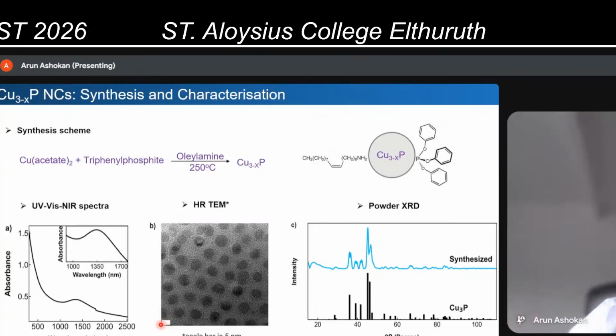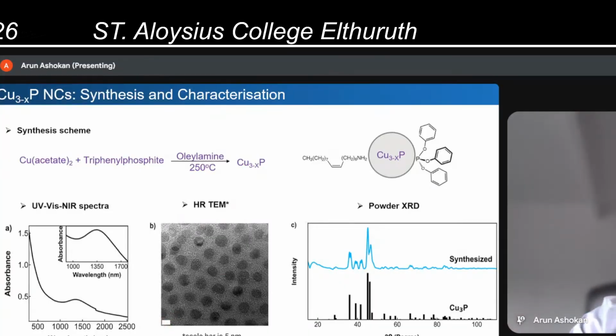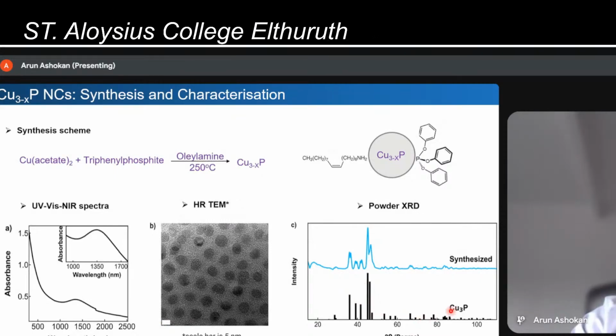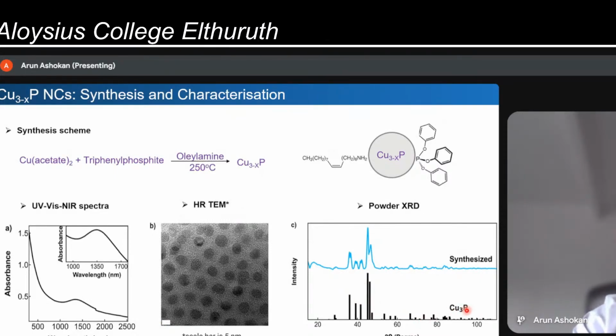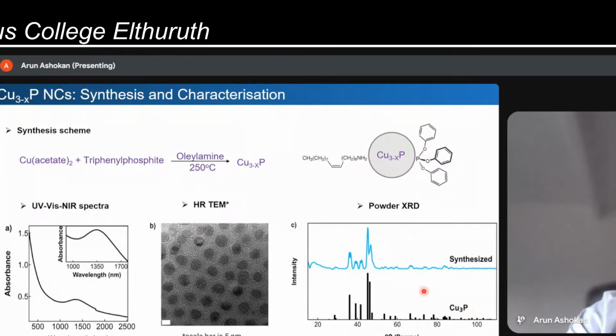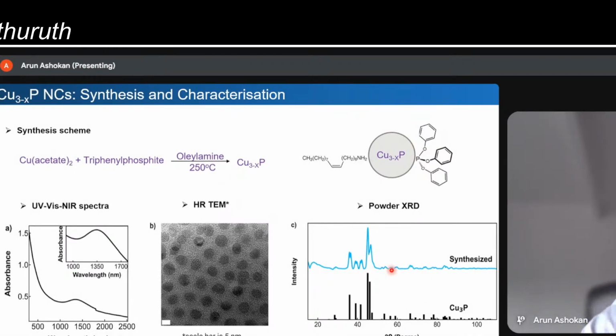And further, if you want to characterize it, we can do the XRD. This is the XRD of bulk copper phosphide, and this is the XRD of the synthesized nanoparticles. So the peaks are matching. So yeah, we basically synthesized copper phosphide nanocrystals.